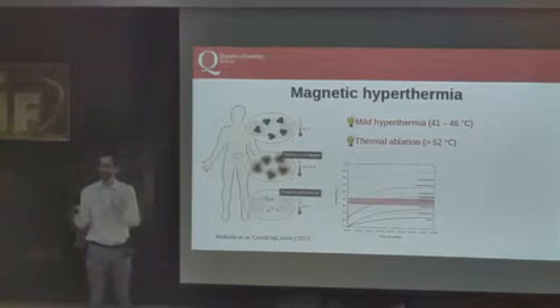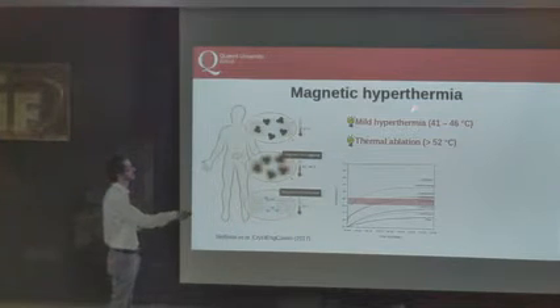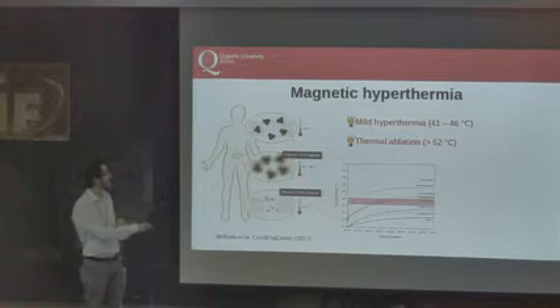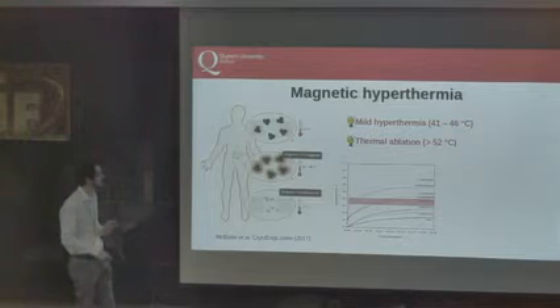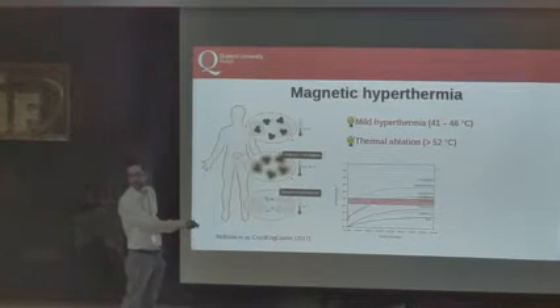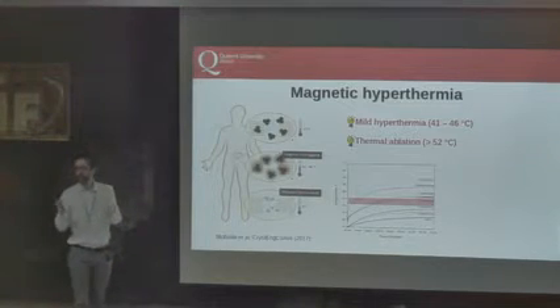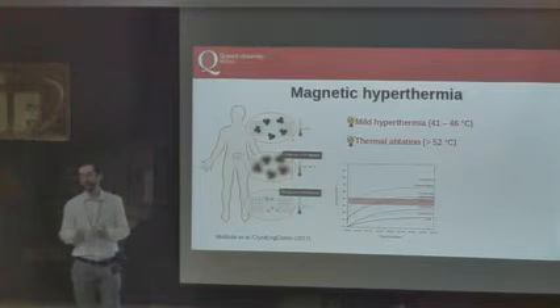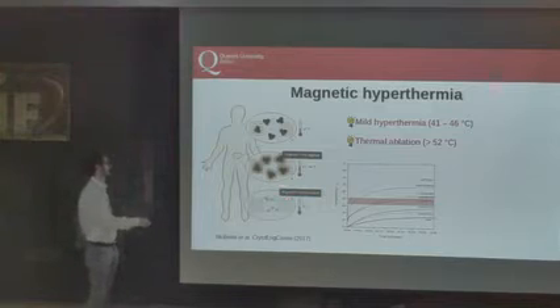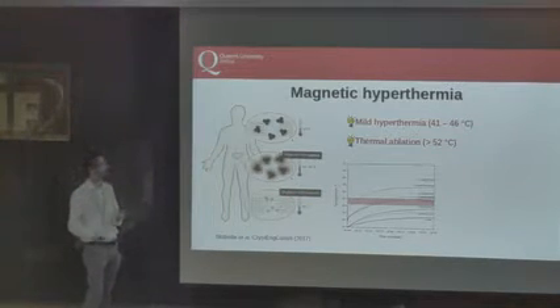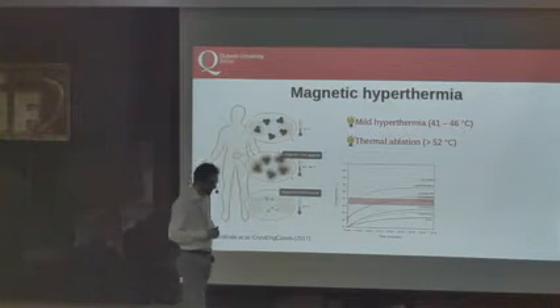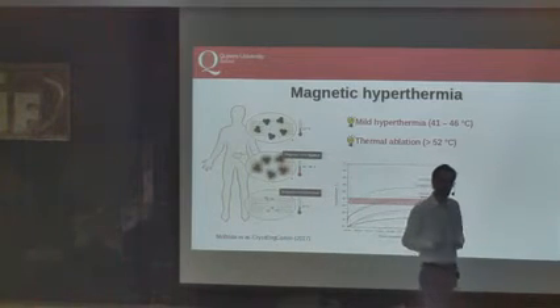From the medical part of this research, the idea is that the best treatment will be done in the mild hyperthermia window, from 41 to 46 degrees centigrade, which is reachable, by the way, with our nanoparticles. When you're supposed to stop the radiation by radio frequency, we can also stop the action of the magnetic nanoparticles, so the heating, and then hopefully the body can get rid of them simply. They hopefully don't stay in the body. There are many uncertainties, probably many more on the medical side, but from the physical and engineering side, our main question is how to target the right window of temperature.